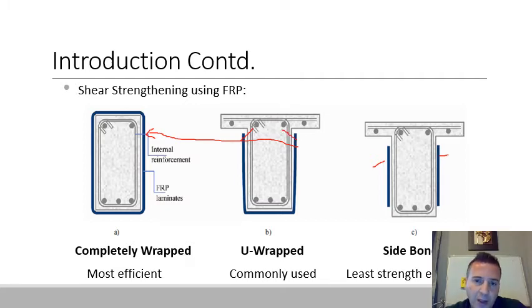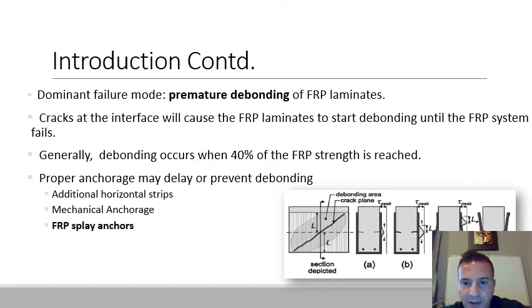That will prevent the debonding of the FRP sheets away from the concrete surface, because a typical failure mode only utilizes 40% of the material strength: after certain loading the sheets will debond away from the concrete. This is the shear failure. Usually cracks at the interface will cause the FRP laminates to start debonding until the FRP system fails, and this utilizes only 40% of the tensile strength of the sheets. A proper anchorage of the sheets will delay or prevent debonding. You can have mechanical anchorage, additional horizontal wraps, or sheets, or you can add FRP splay anchors. And the topic today is to fasten or bond these sheets with FRP splay anchors.